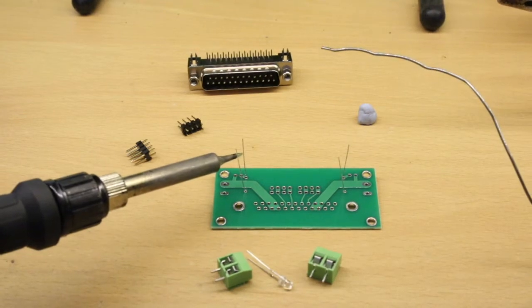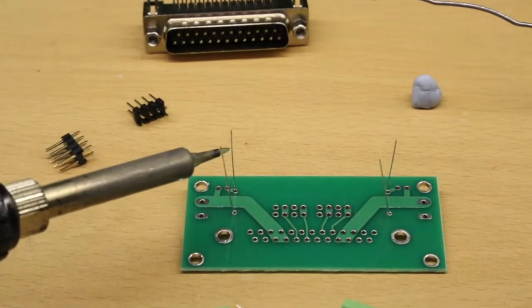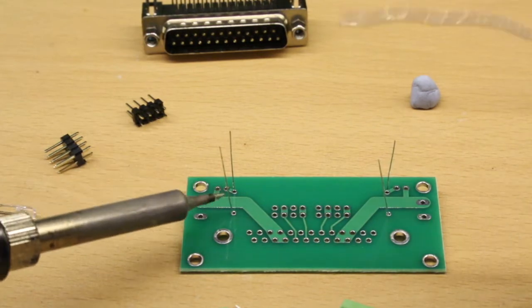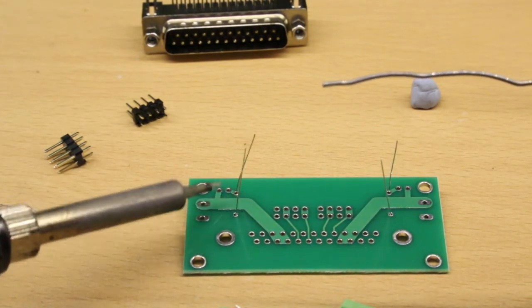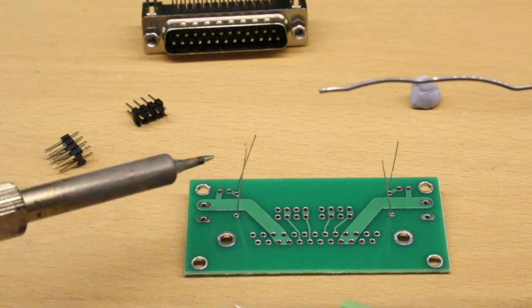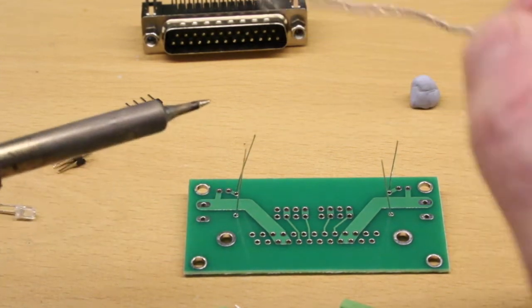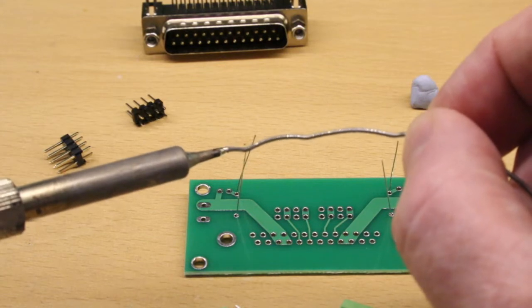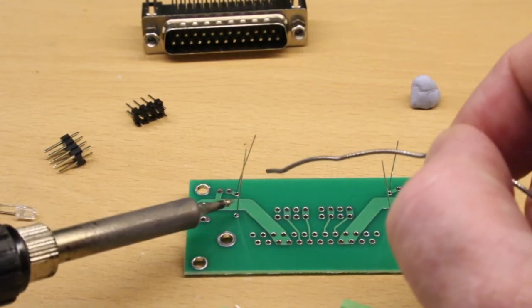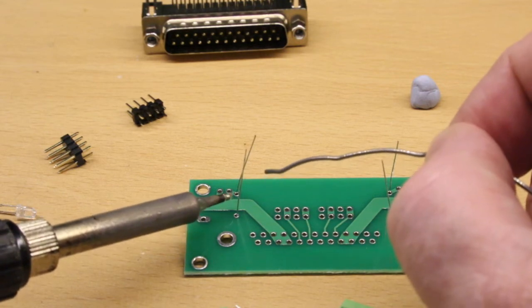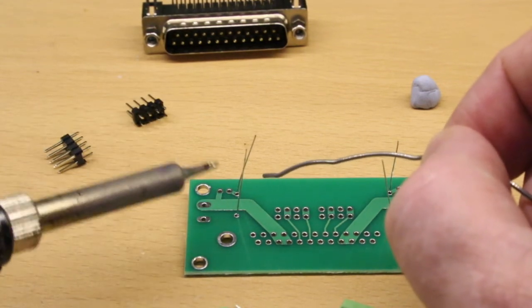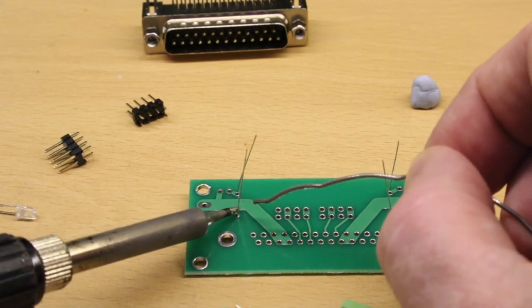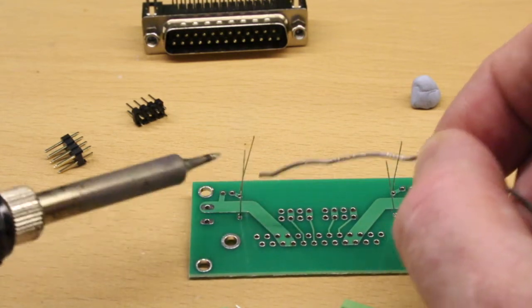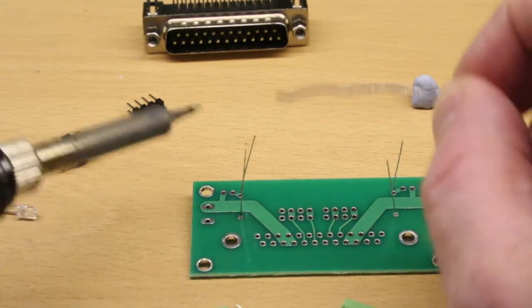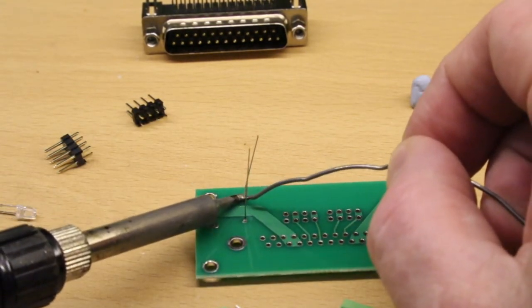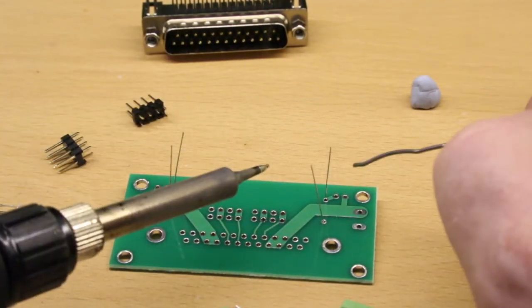So if I zoom in here as I do this, you're trying to make a joint between the metal of the component and the metal that's exposed on the actual board. So the way you do that is, first of all, make sure there's some solder on there, so that will give you a good thermal connection between the two. And what you're trying to do is not get solder from the tip onto the two components, but just use the solder that's on there to make enough heat, and then when the solder goes in, it effectively bridges between the two, and then it makes a nice soldered, well, almost like a welded joint.